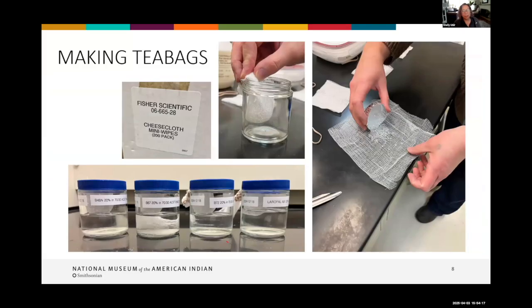For the tea bags, we use this medical gauze with a loose weave just tight enough to carry the pellets without them falling through. The finished packet needs to be long enough to just touch the solvent at the top and then come together outside the jar. So in our case, we used an 8-inch or 20 centimeter square piece for each solution. We held them together with a rubber band at the top, which goes outside the jar.